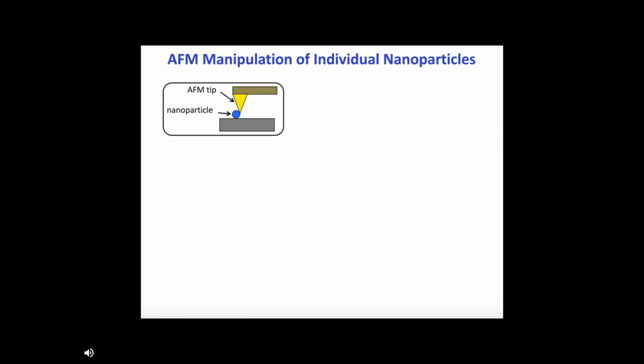Lastly, before wrapping up here, I just want to answer the question of how we're able to take a single one of these nanoparticles and place it at the exact location on the sample where we want to measure temperature. That's, of course, very critical, because if we don't have a way to do that, then this whole technique really falls apart. And so the approach that we take here is that we use an atomic force microscope tip, or AFM tip, to push individual nanoparticles around on substrates and place them at the location where we'd like to measure